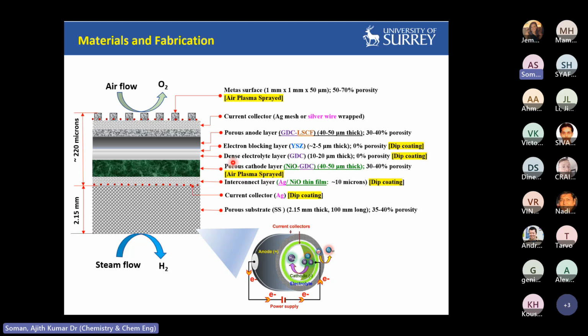And we also have a dense electrolyte layer and blocking layer. This is a bilayer electrolyte combination. Both can be achieved by dip coating. And finally, we have an anode layer as a GDC and LSCF combination. The thickness is about 50 micron. So it's the closing stage of the structure. And finally, we have one more connecting layer to supply the electrons, again silver mesh in the form of silver wire that we wrap onto the top. And the microstructure is playing a vital role in the electrode surface, either by dip coating or air plasma techniques. So we have a modified microstructure on the cathode, where it converts most of the steam vapors into hydrogen in an efficient manner.